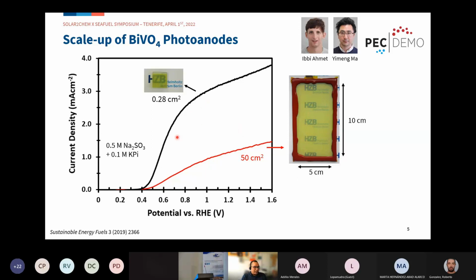As soon as we did that, the IV curve shown here under AM1.5 illumination shows we decreased the photocurrent significantly when we went to 50 square centimeters. In fact, we only have about a third of the photocurrent we have at the small scale. The question is, of course, what causes this decrease?